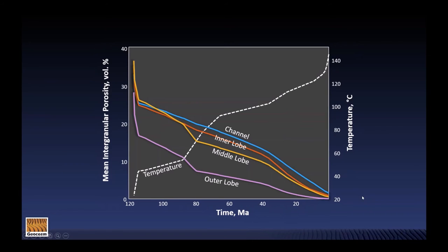So the interesting thing to think about here is if you're looking at analog samples and you have analogs that have very high thermal exposures, the relative difference between facies that you observe may not be a very good guide for what that difference was in the geologic past, or what that difference might be if you looked at the same composition and textured rocks that had been exposed to a lower thermal exposure. So anyway, I hope this gives you a feeling for why we're seeing differences between these two fans and how they evolve through time. Now let's go on and consider the spatial distribution of rock properties.